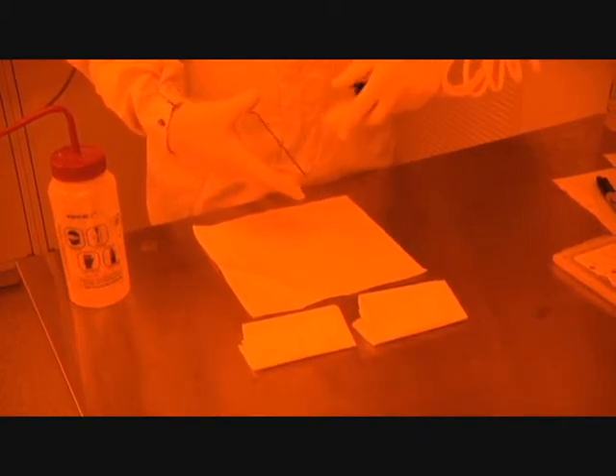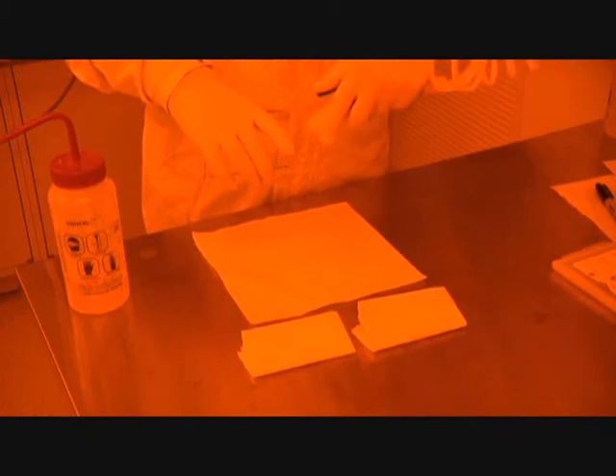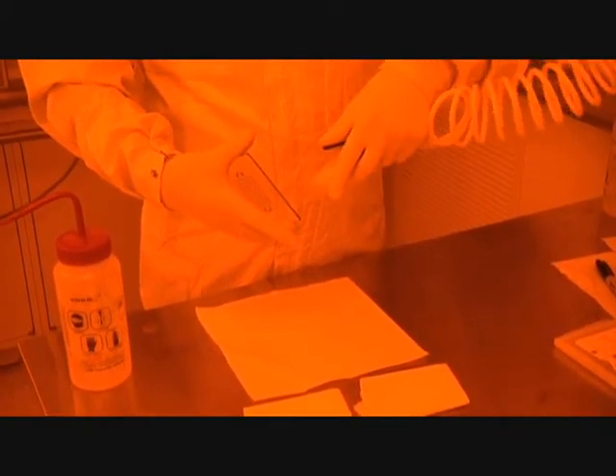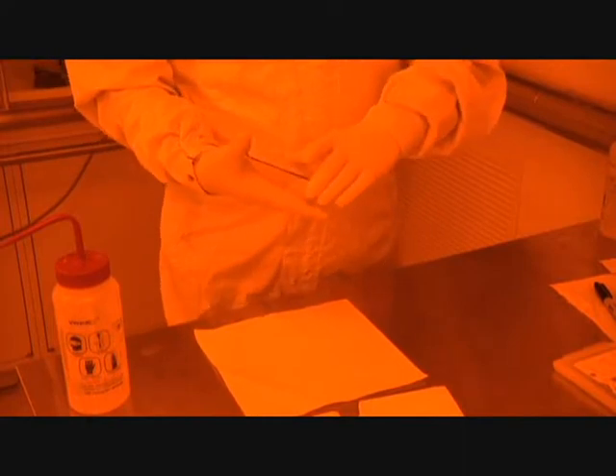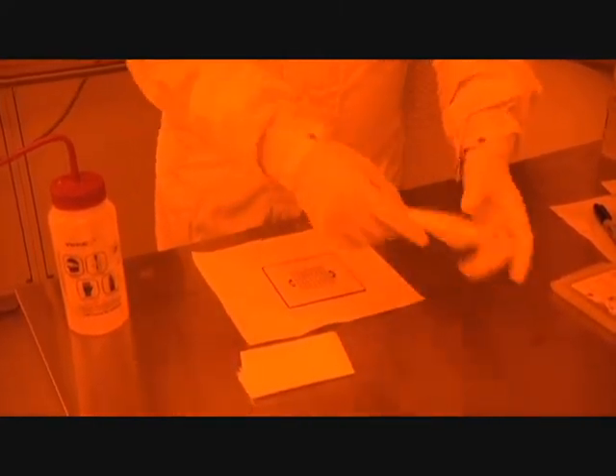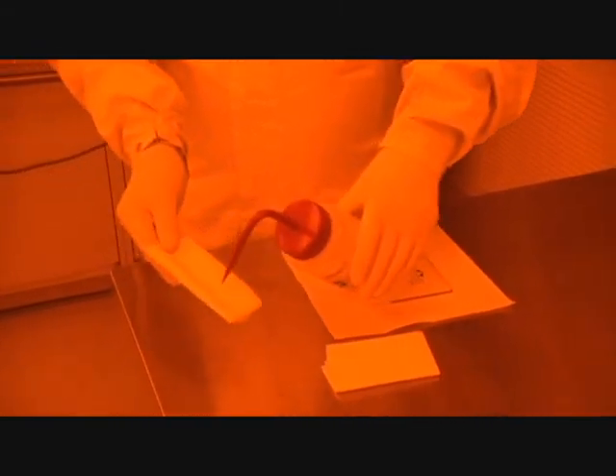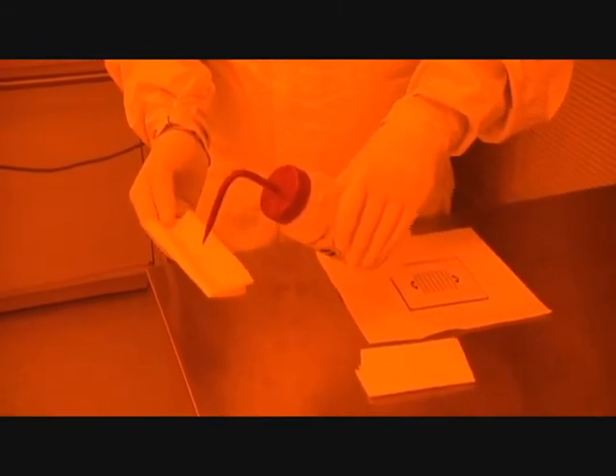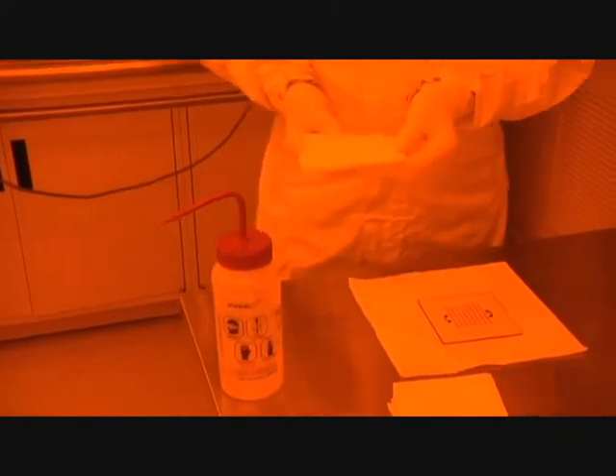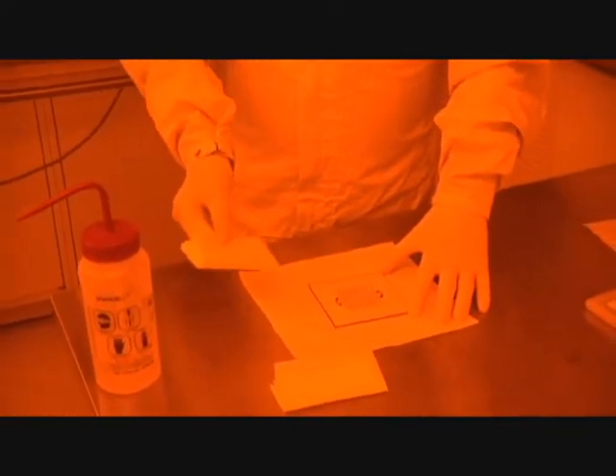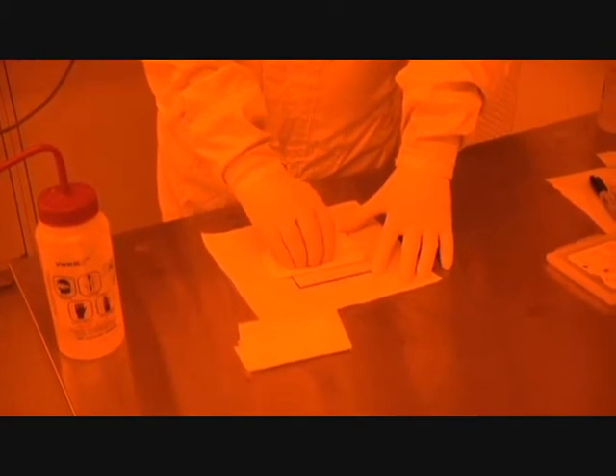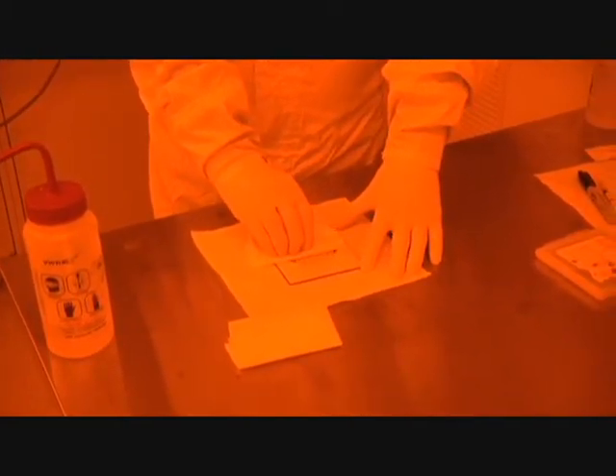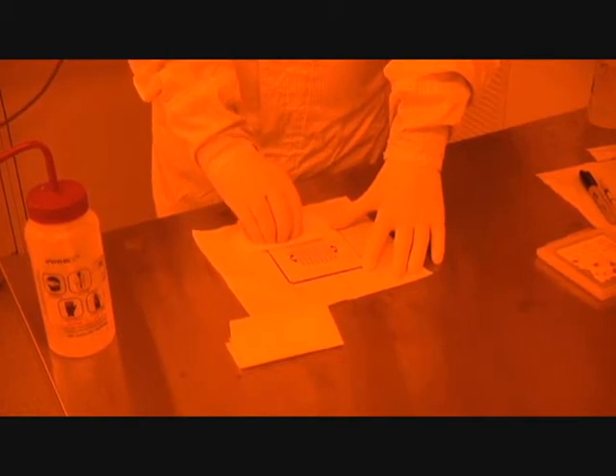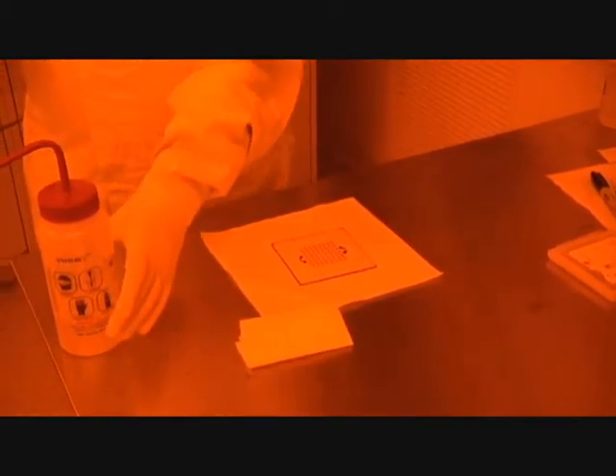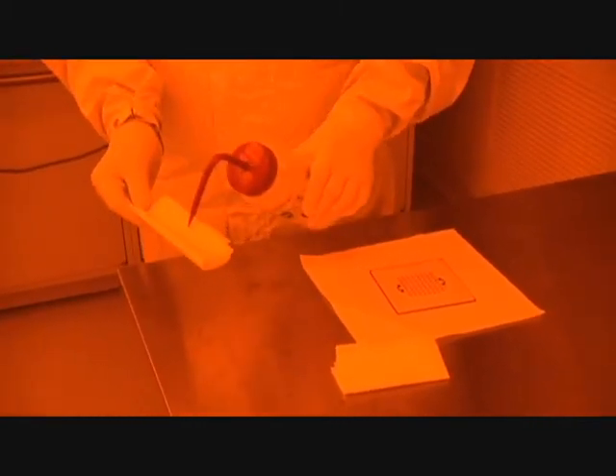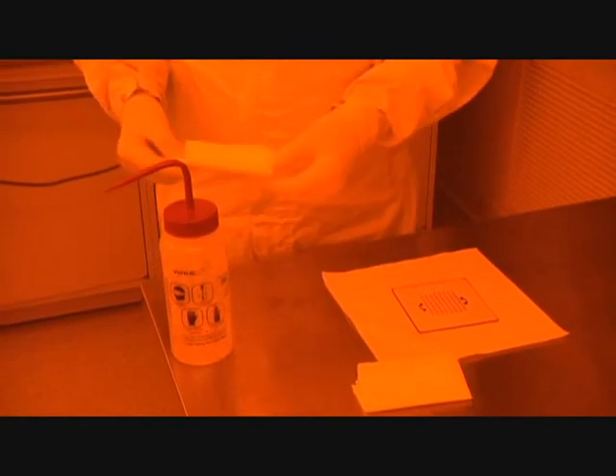And what's going to happen is this chrome mask, just to make sure it's fairly free of photoresist and so forth from previous runs, we're going to wipe it down with some lightly soaked wipes with acetone. The way we normally do this is in something like overlapping quadrants that we wipe down. So we'll go over one quadrant here, bearing down pretty hard and dragging the wipe, and we soak the other side of the wipe and do the next quadrant.